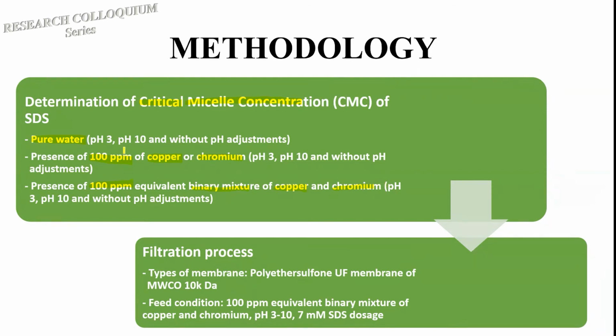Not to forget to mention, the pH of all three systems is adjusted to pH 3, pH 10, and also without any pH adjustment. So after we determine this CMC, eventually we will carry out a filtration process, using a polyethersulfone ultrafiltration membrane, with a molecular weight cutoff of around 10k Daltons.